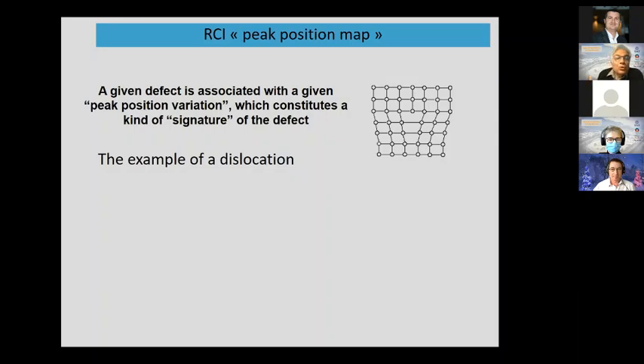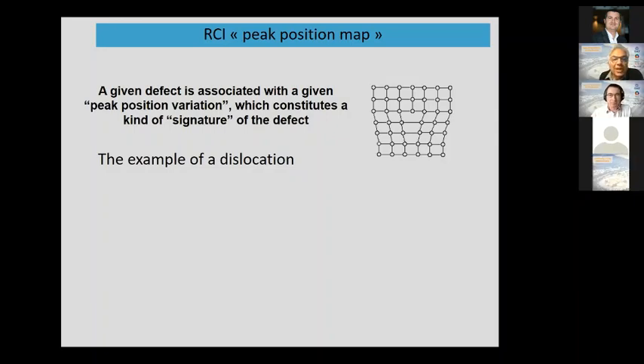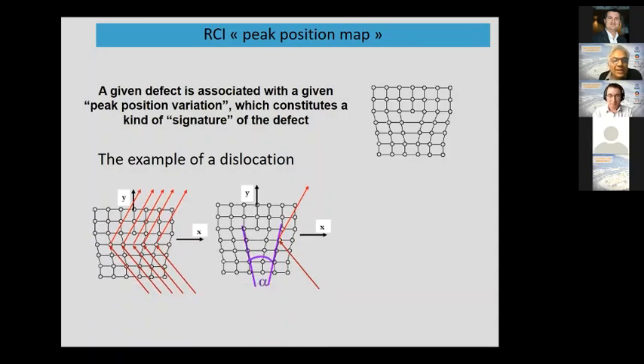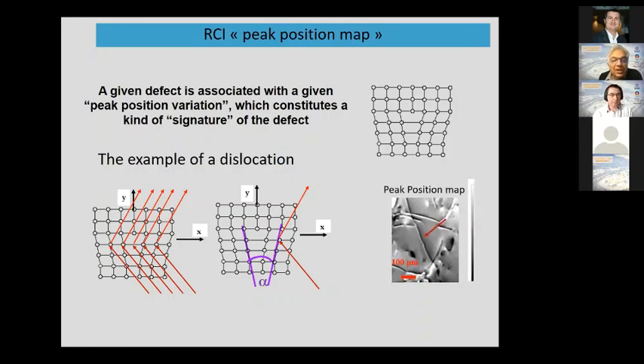Well, the peak position map also allows identifying the defects, because a given defect is associated with a given "peak position variation", which constitutes a kind of signature of the defect. Let's look at the example of a dislocation. If you do Bragg diffraction on these planes like that, you see that from one side to the other of the dislocation, you have a variation of orientation, and so a variation of peak position. And that is what you can see on the peak position map, where you have the matrix having a given position, which is gray, and around the dislocation, white and black, that is higher and lower peak position than the matrix. This is a signature of the dislocation.